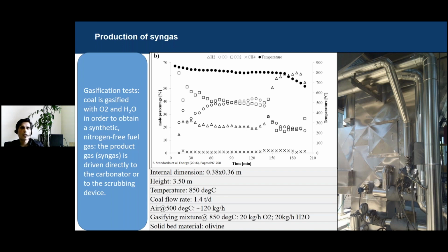This is, as I told before, a 500 kilowatt thermal bubbling fluidized bed. And in this reactor, we are able to simulate any composition similar to the gas leaving the blast furnaces or even the basic oxygen furnaces case. So we can replicate the same conditions of the gas leaving the steel mill. So we can have a figure and an estimation of how efficient calcium looping is for the decarbonization of the steel mill.